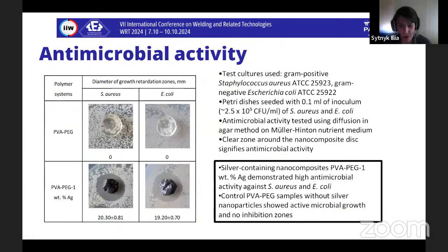To study the antimicrobial activity of nanocomposite samples, reference strains of opportunistic pathogens were used as test cultures: gram-positive Staphylococcus aureus and gram-negative Escherichia coli. The antimicrobial activity of nanocomposites was studied by diffusion in agar on the Mueller-Hinton nutrient medium. Petri dishes with Mueller-Hinton nutrient medium were seeded with 0.1 milliliters of inoculum of test cultures of both microorganisms, Staphylococcus aureus and Escherichia coli. Pre-made nanocomposites with silver nanoparticles were cut into discs with a diameter of 10 millimeters and placed on the surface of the nutrient medium seeded with test microorganisms.